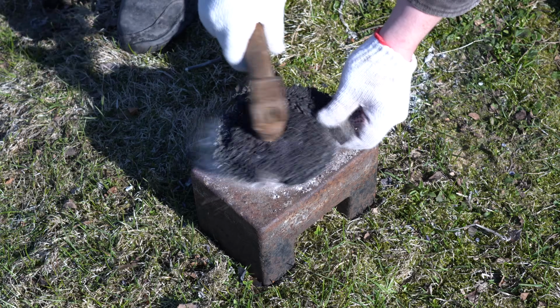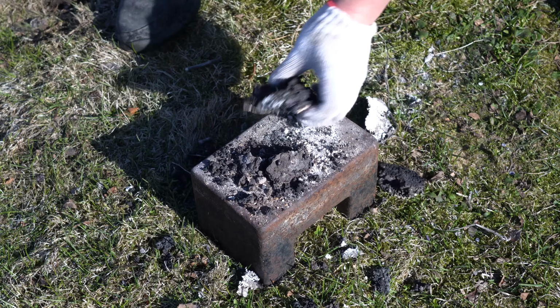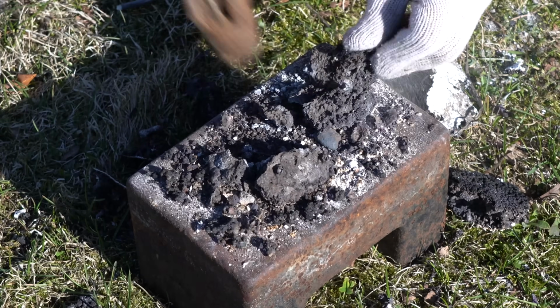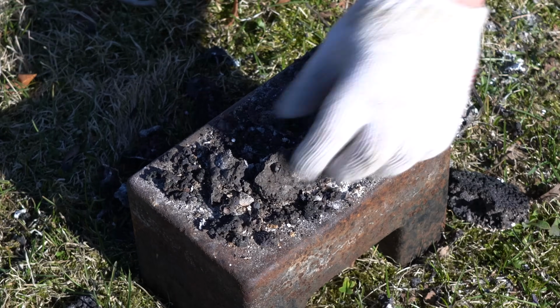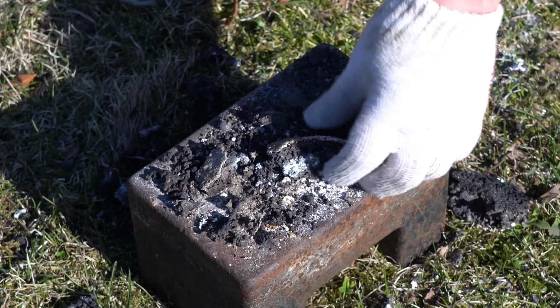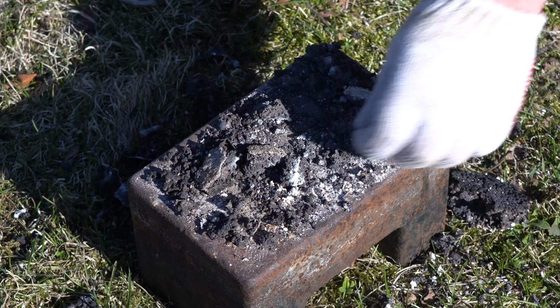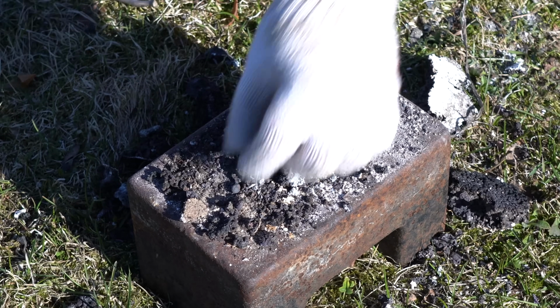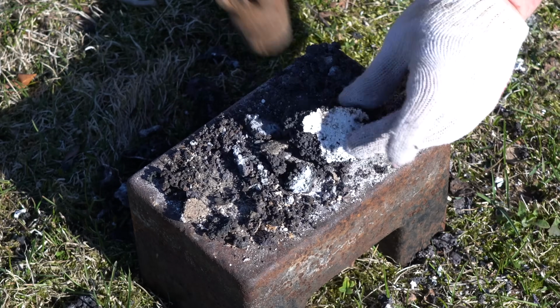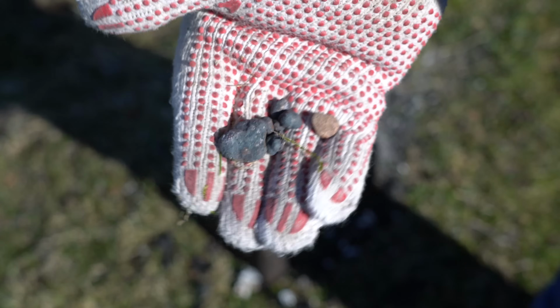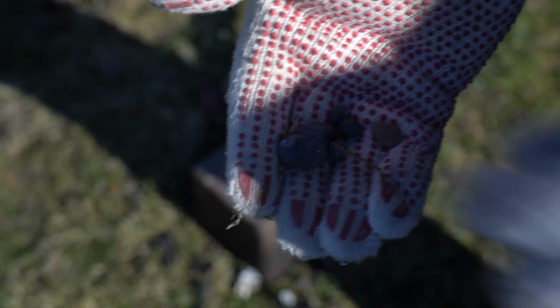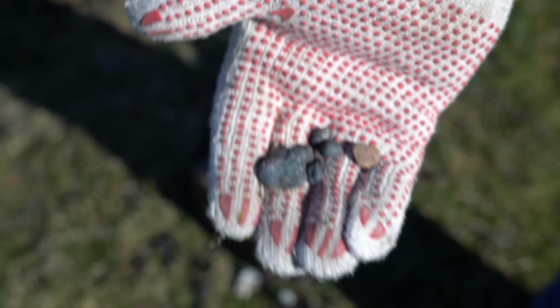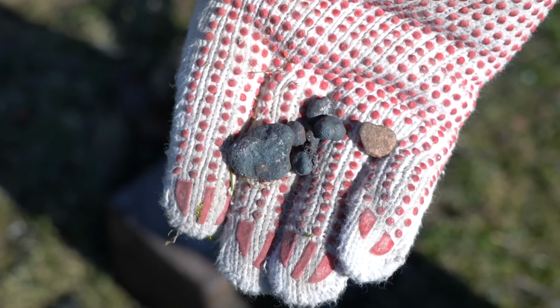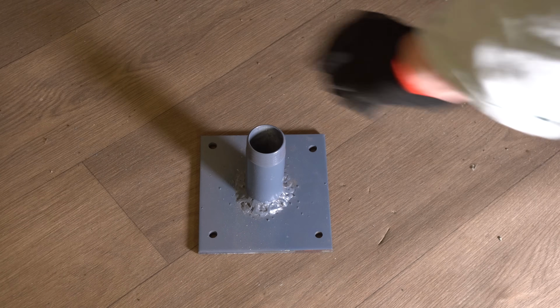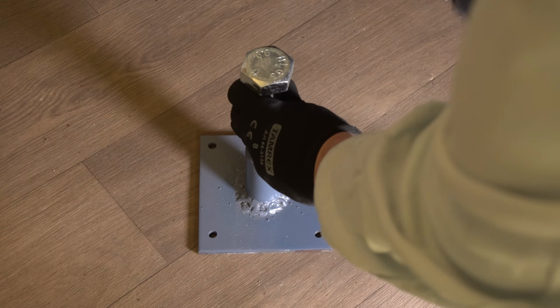After cooling off, however, I was in for a disappointment. Seems like this time I used an excessive amount of flux and slowed down the reaction too much, which is why there wasn't enough time for the formed drops of stainless steel to bond together before hardening. That is why this time I managed to get only a few drops of stainless steel instead of a big nugget. I need to improve the mixture somehow, but first I need to grind some magnetite for the next attempt again.